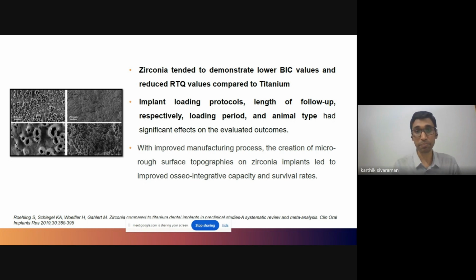values compared to titanium. The authors also felt that with improved manufacturing process and the creation of micro rough surface topographies on zirconia implants, there is an improved osseointegrative capacity and survival rate. So the previous or older versions of the zirconias which were introduced and used were not as good as the ones which are commercially available now. Currently, when you look at the zirconia implant surfaces, they are subjected to acid etching or sandblasting, and they have demonstrated better bone implant contact and better osseointegrative capacity.